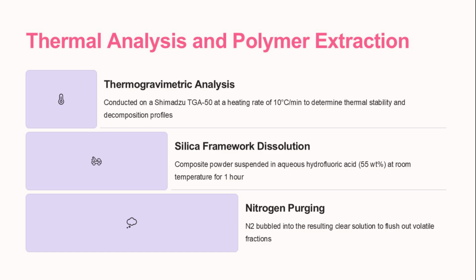To extract the polymer component, we suspended the composite powder in hydrofluoric acid, 55% concentration, at room temperature for 1 hour. This allowed the silica framework to dissolve, leaving behind the polymer. Finally, we bubbled nitrogen gas through the resulting clear solution to flush out any volatile fractions that were released.